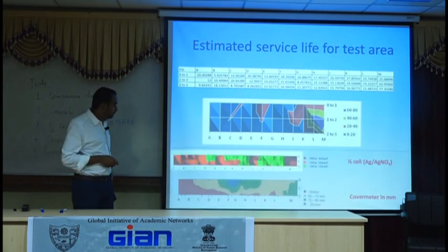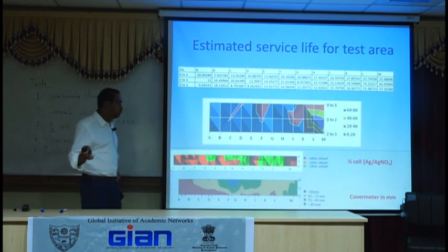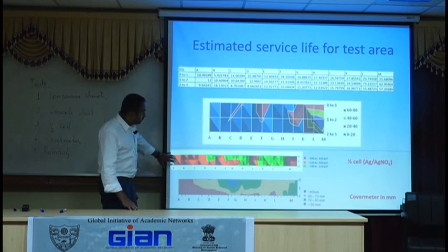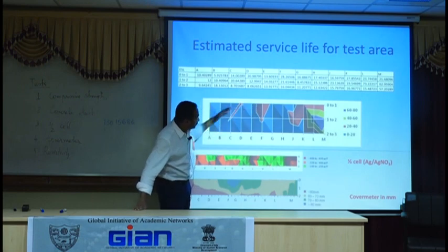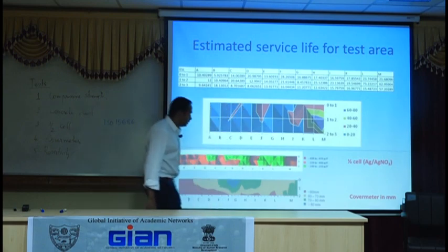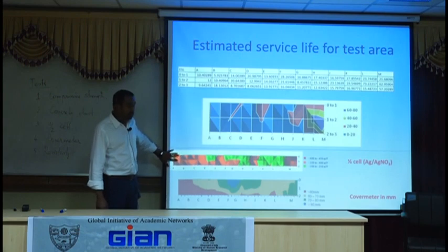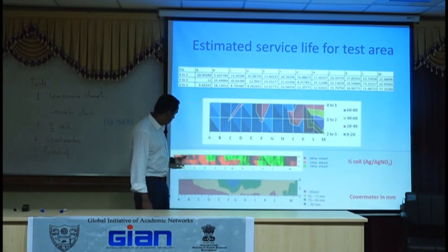It's mathematical. What I have on top of it, I have half cells. So I can put it back into half cell and see, is that what I'm getting? Or is half cell telling me a different story? Okay? And if you look at it, the top part of it where the service life is reasonably good, service life is low in these regions, okay? The blue regions. And that's moderate half cell. And extremely low half cells are found here, where the dark patches are.